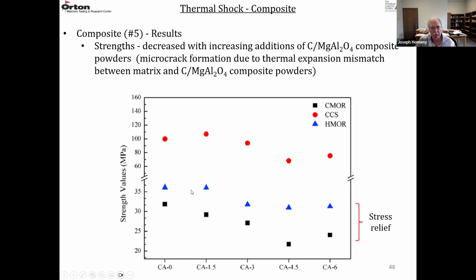And when they measured the strengths here, it's going from CA-0 to CA-6, so they're increasing the amount of the carbon spinel powders. The solid squares are the cold MOR, the blue triangles are the hot MOR, and the red circles are the cold crushing. There's a break in the curve here because these materials are always much stronger in compression than in bending, which is basically a tensile failure. So there's a tendency for any of these strengths to decrease with the additions of the carbon spinel composite powders. They attributed that to microcrack formation due to thermal expansion mismatch between the matrix and these composite powders.